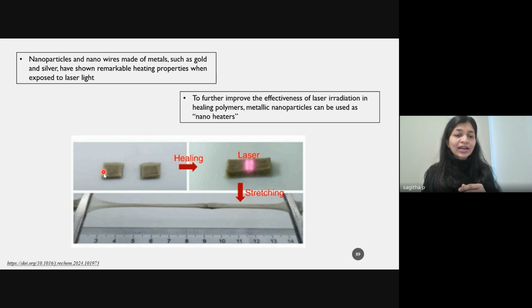In this work, they added silver nanoparticles as well and prepared the polymer material. They cut this polymer material into two pieces, and since silver nanoparticles are incorporated in the material, the silver nanoparticles have the ability to provide the required energy to bond these materials together. They first prepared the polymer-based self-healing material using NIPAM polymer and silver nanoparticles as the heating agent, and then applied laser radiation between the cut edges. Within 1 minute they observed that the material showed the self-healing property and the material joined together.